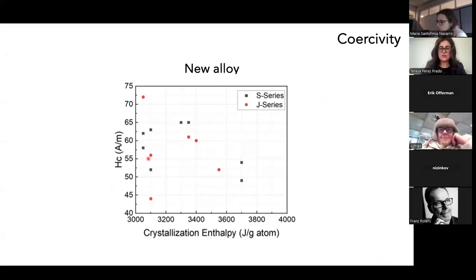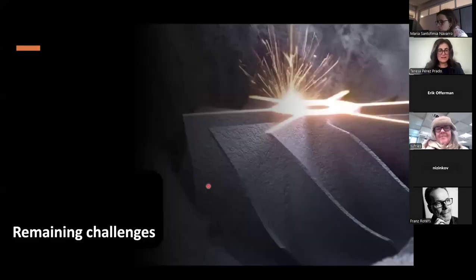How are we doing in terms of coercivity? This is the range of values that we obtain for the new alloy within all these windows. You can see that we are now down to the 40 to 70 range. So the decrease is significantly higher. Still, we are not at the level of the Metglas ribbon, which is 10, but we are getting there, and this is a future challenge. So just my last two slides, these are the remaining challenges, and mostly two things.